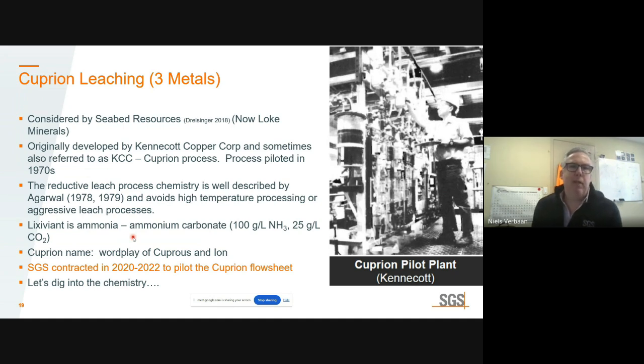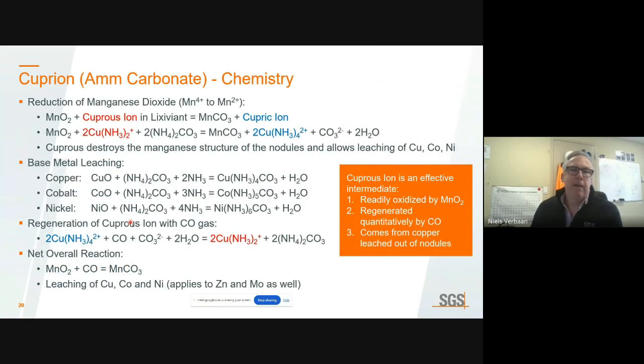It's worthwhile to dig into the chemistry here a bit, and I'm going to try and simplify it in the next few slides. To explain Cuprion, I think it's good to divide this into three main steps. The first step is the reduction of the manganese dioxide, which is the bulk of the nodule, and within this reduction, we destroy the crystal lattice. It's the cuprous ion that reduces the manganese from 4 to 2, and it produces a cupric ion. The actual reaction equation is shown here. And as the manganese structure is destroyed, this allows the leaching of copper, cobalt, and nickel into the lixiviant.